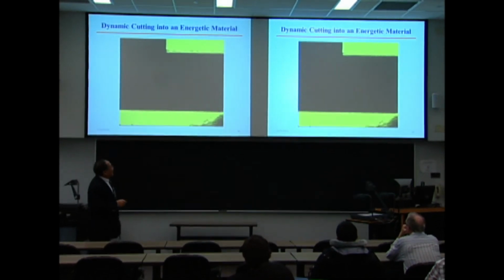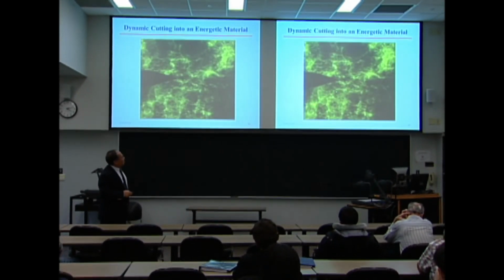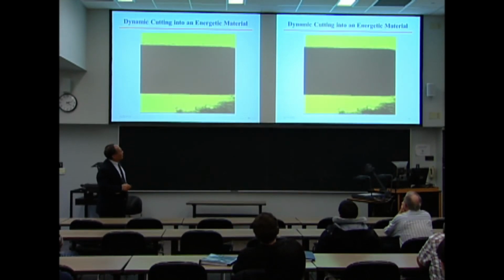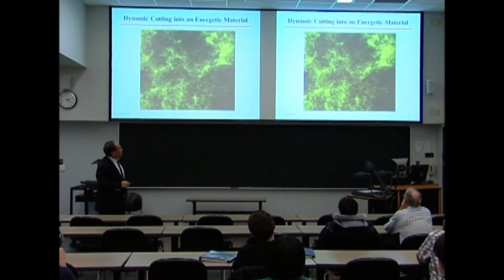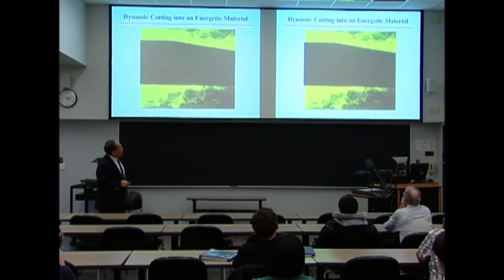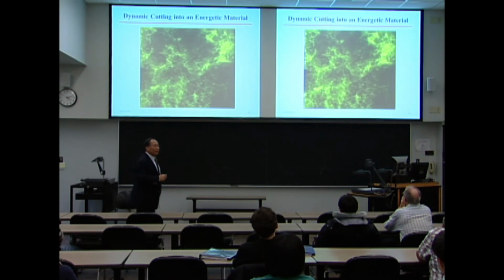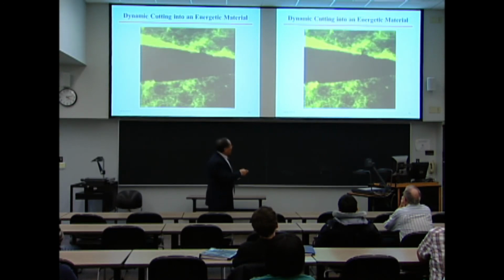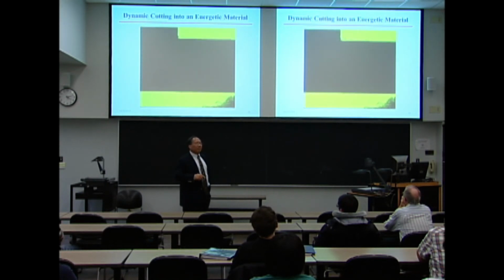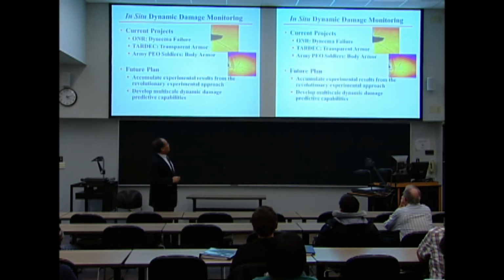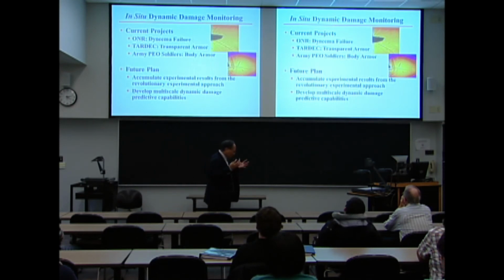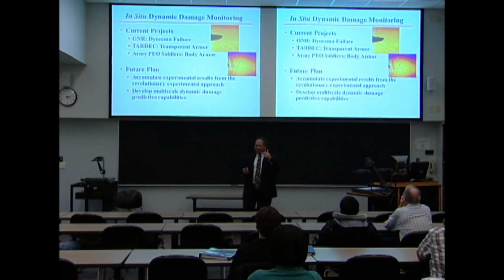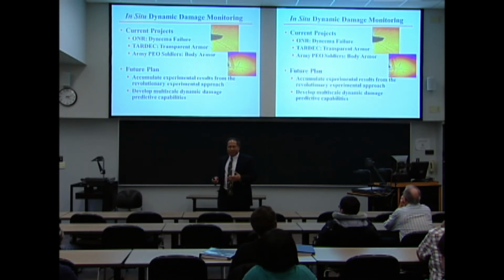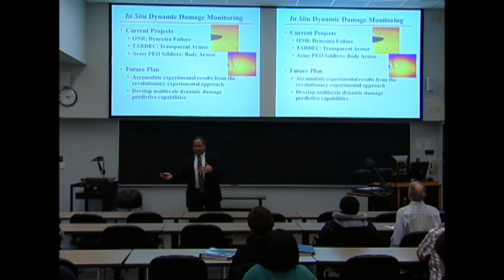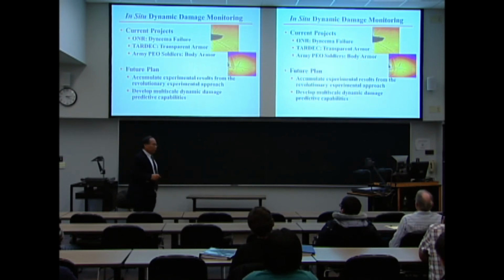So this is safety for energetic materials. We have simulants of the energetic materials that get punched into by a sharp object, and we can characterize the deformation field around the punch. So that's one effort we started building to characterize the high rate response of energetic materials. All right, so that's the more recent fun we've been having. We're using this X-ray to see anything inside that's breaking up. Some of them we can explain, quite a lot of them we cannot explain because this is a very different angle. So what's the future?